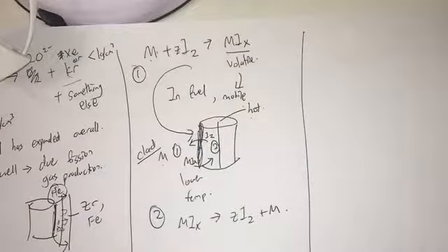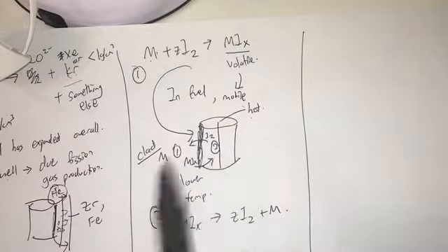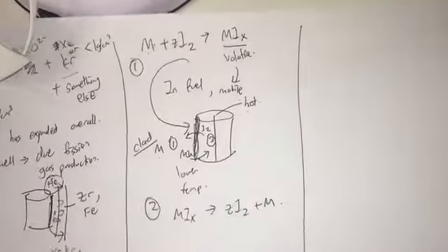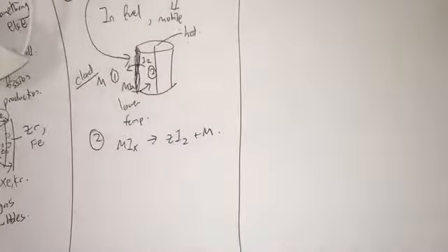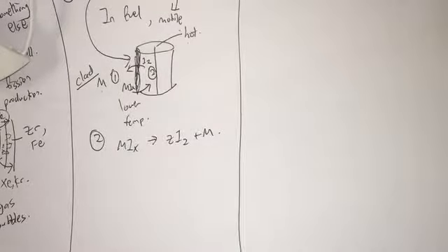So this can cause a very interesting effect. Metal is effectively being transported from the outside, especially if the fuel is touching the cladding, into the inside. So this kind of corrodes the cladding, and this causes the migration of the metal. So this is what a halogen can do. That's the chemistry that's going on there. Now let's move on to other elements.